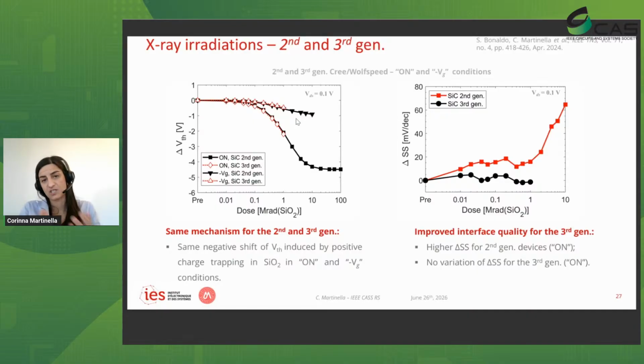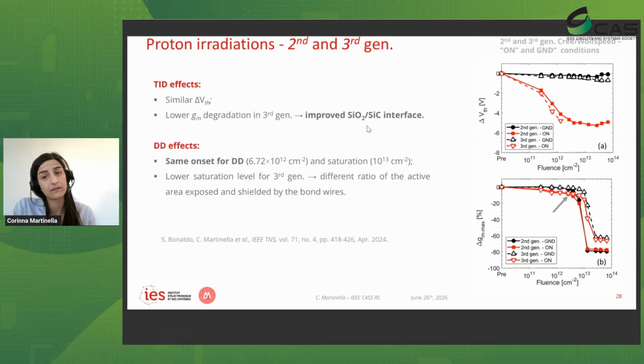However, when we look at the subthreshold swing, or at the transconductance, we can see that there was actually a higher increase in the second generation devices, meaning that the third generation devices have a better interface with respect to the previous generation. The results before were collected with X-ray radiation. Then we did the same with protons, and we basically observed the same results. Of course, the onset for displacement damage was happening exactly at the same point for these two technologies. However, you see a different residual current, and this is simply due to the different proportion of shadowing due to the bond wire that we use in our setup.